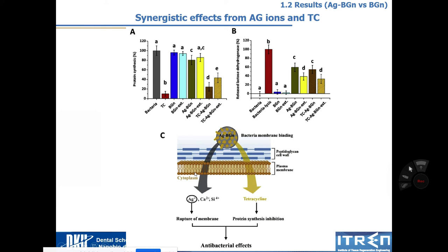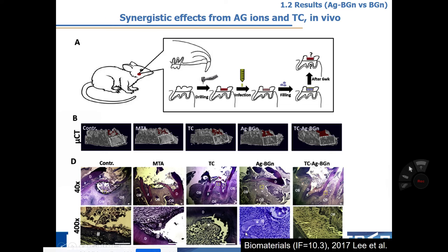And then we can assume that when this Ag-BGn interacts with the bacterial membrane, it more successfully and efficiently delivers tetracycline, which was loaded in the nanoparticle, as well as silver. And then this rupture of the membrane from the silver and protein synthesis inhibition from tetracycline co-ameliorate the antibacterial effect.